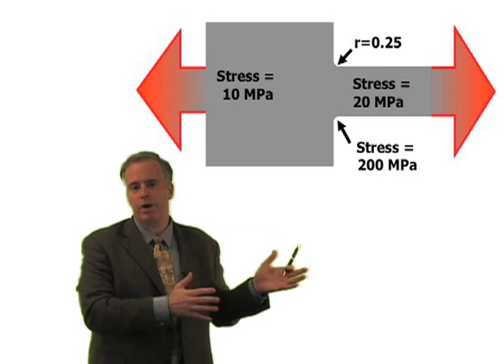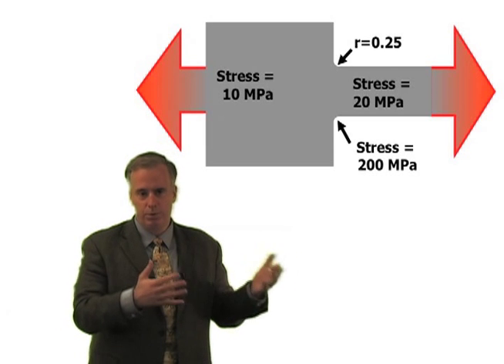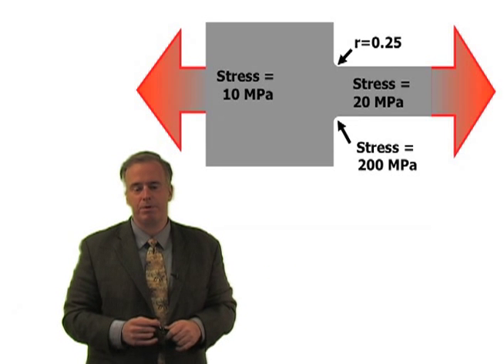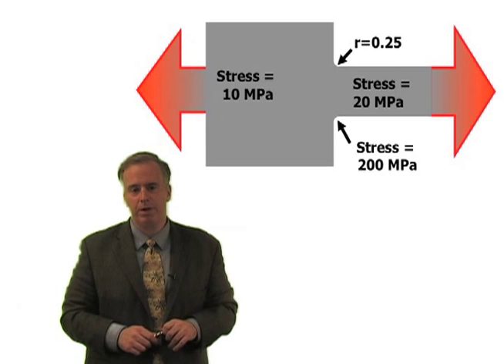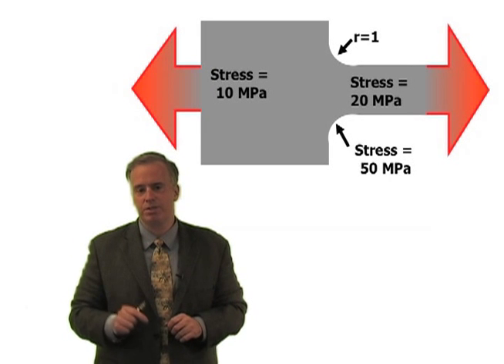So we can work really hard on the grinding operations, and we can do that if we have to, to reduce those temperatures. But quite often, the easy answer is let's just make that radius a little bit bigger. Those stress concentrations are not as big.